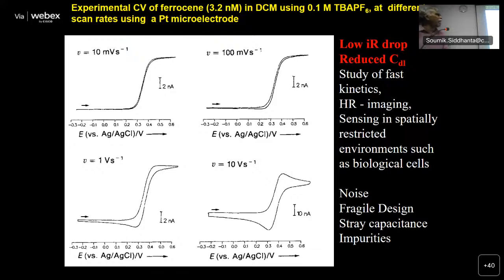So these electrodes are called ultra-microelectrodes. You can go to very high scan rates, 1 volt per second, 10 volt per second. You can imagine, with the same size of electrode, as you change the scan rate, you can see how the voltammetric shape changes. And remember the currents are in nanoamperes. Femtoamperes can also be measured by using this technique. With an ultra-microelectrode you can go to 50,000 volt per second. Many redox proteins can be investigated by using fast scan voltammetry.